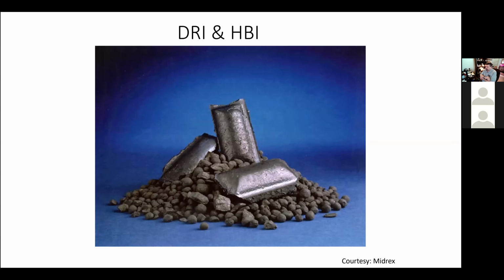And when I talked earlier, I said, well, sometimes we've got to add some cleaner materials that have low residuals. So these would be materials like DRI, direct reduced iron, and HBI, which is hot briquetted iron. It's just basically these same pellets taken while they're still hot. They come out of the process reactor and go directly into a briquetting machine, and they make these nice briquettes.